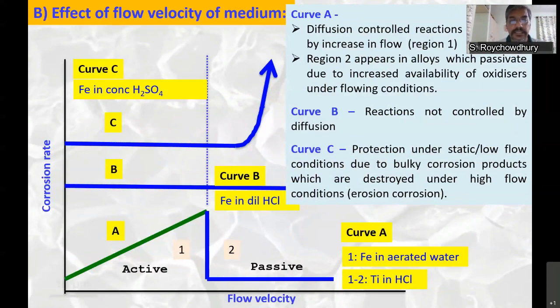If these oxidizing agents do not reach the solution or reach the surface of the metal, the passive film will not form and it will keep on corroding. Whereas in flowing conditions, what happens? It aids in delivery of these oxidizing species or oxygen to the surface of the metal and helps in passivation. So in flowing conditions, it will passivate easily. So for metals which passivate, it's good. It performs well in an oxidizing environment, also in flowing conditions.